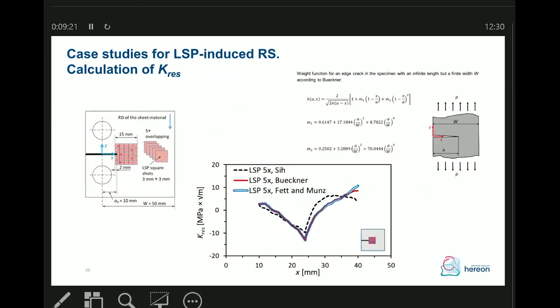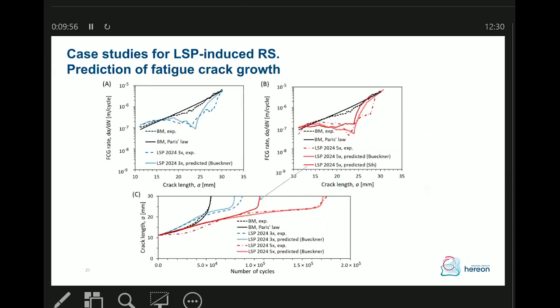Next slide. And here are the calculated solutions from applying the weight function method for the stress intensity factor due to the presence of residual stresses. As you can see, we only have disagreement if we consider the solution where we do not consider the finite specimen width. For the CT50 specimen geometry, it's important to use a solution where we consider the finite specimen width. Continue. And here are the results of prediction. Again, we only have disagreement if we use a solution that does not consider the finite specimen width, but in other cases we are in very good agreement with the experimentally obtained results.